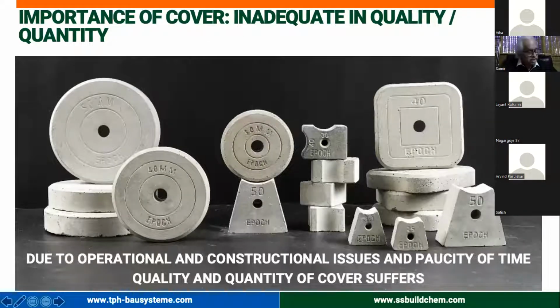Basically, to take precautions, we should have very good quality bar spacers. We are using bar spacers that are not healthy. If you have a look at it, these are very healthy bar spacers. Bar spacers have also got a code of practice, and these are tested. These bar spacers are of good quality. These are tested. This is approved even by the bullet train project. It is tested for sustainability. That means this is made out of green concrete, and it is tested for durability, that is, for rapid chloride testing. So use a good quality.